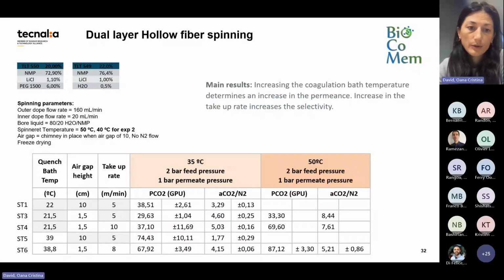And then we also checked gas permeation of these membranes. The membranes that were made at a higher quench bath coagulation temperature have a much higher carbon dioxide permeability, and the membranes that were made at a higher take-up rate somehow have a higher selectivity. So we can see how spinning process parameters can influence gas permeation properties and the final properties of the membrane.